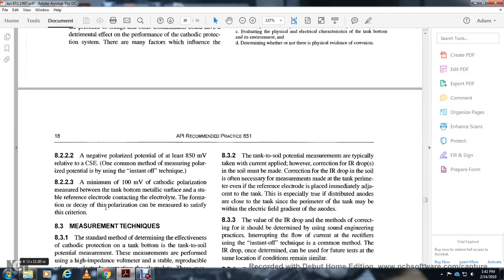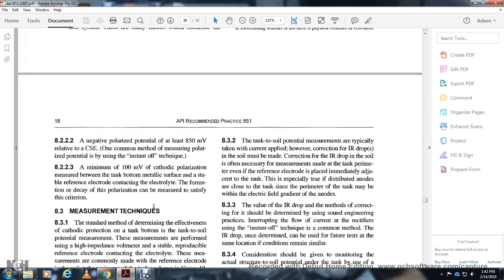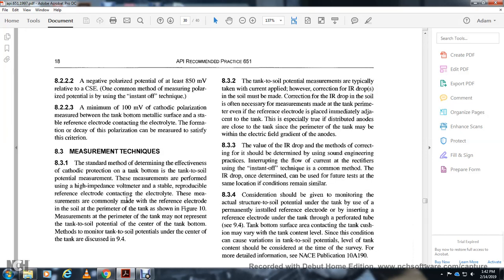A minimum of 100 millivolts of cathodic polarization measured at the tank bottom, and a stable reference electrode contacting the electrolyte, with formation and decay of the polarization measured, satisfies the criteria. 8.3 Measurement techniques.